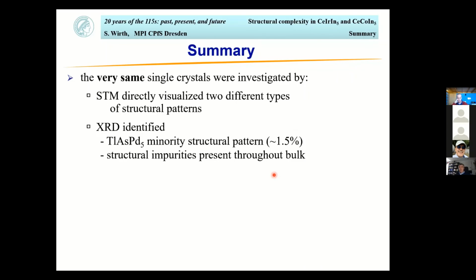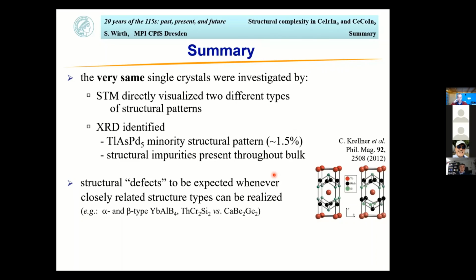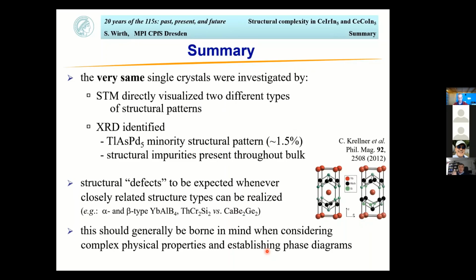Now, why would we worry about 1.5%? First of all, these structural defects, as I would like to call them, can be expected whenever two or more closely related structure types can be realized. And that's also seen, for instance, in our beloved 122 structure here. And of course, the point is, if we look at very fine details of the phase diagram, and sometimes we talk about 1 or 2% of the electrons, then we should keep in mind that that could be simply caused by, or at least supported by, such structural imperfections.